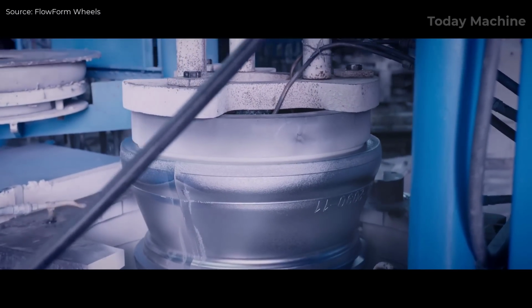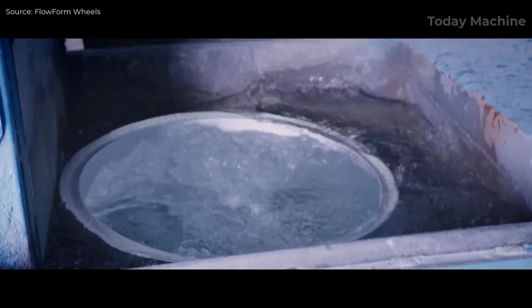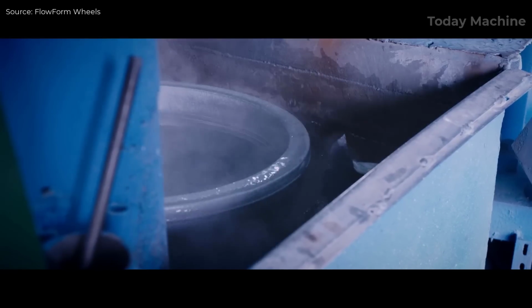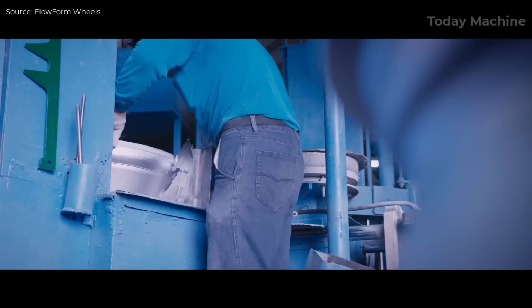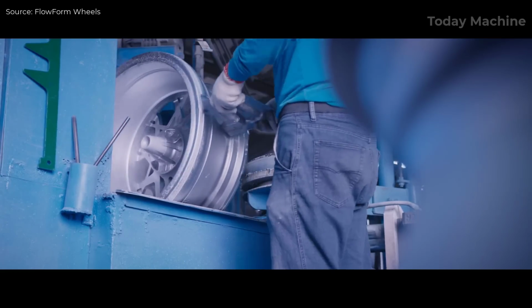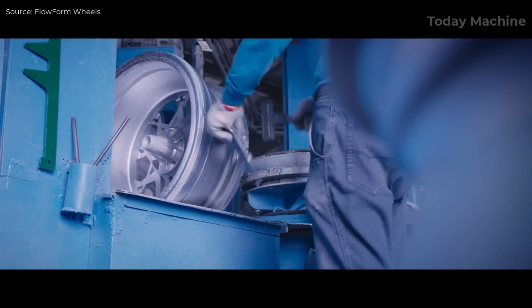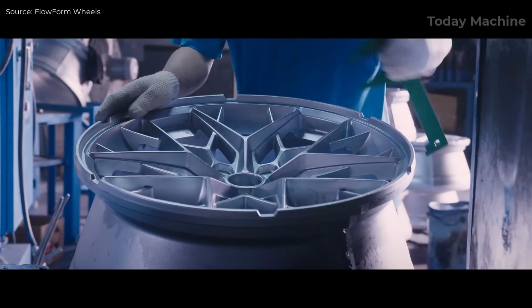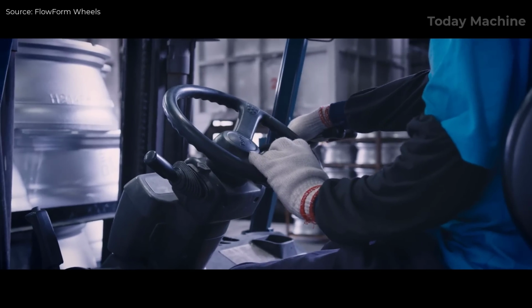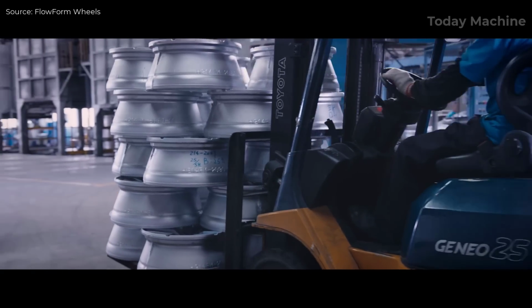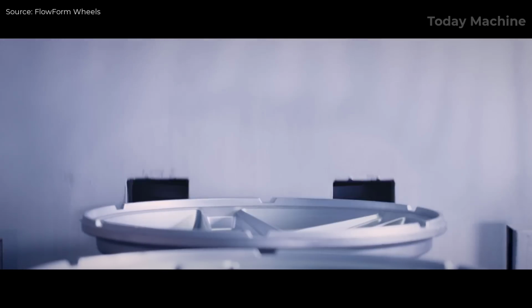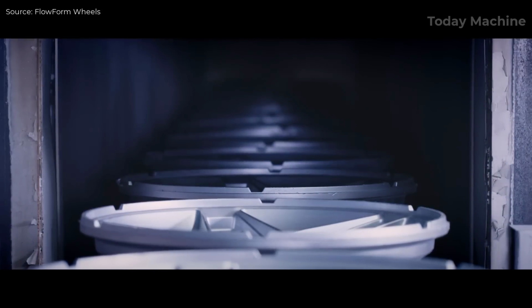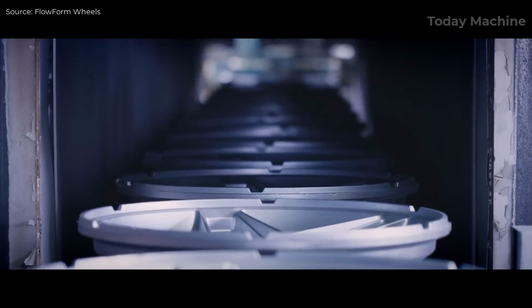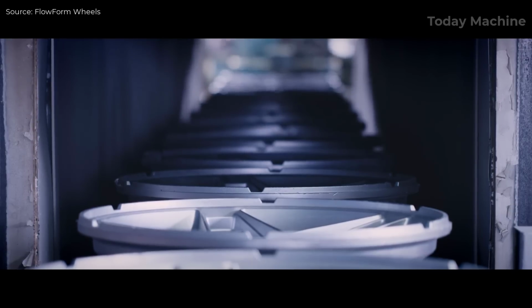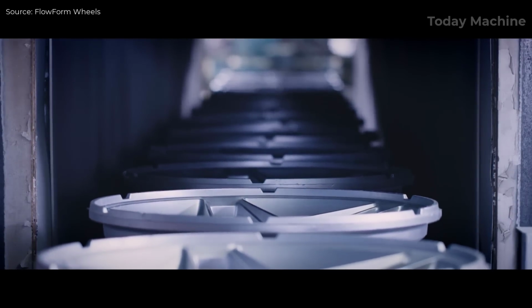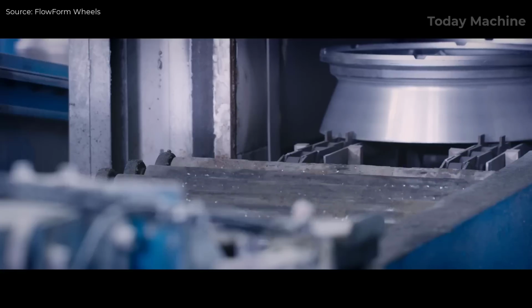Once the aluminum solidifies, the casting is removed from the mold and quenched in water at around 120 degrees Fahrenheit, 49 degrees Celsius. Any excess material, known as flashings, is removed, and the wheel's dimensions are verified to ensure it meets the correct specifications. At this point, some of the wheel's spoke design can be observed, but one key characteristic of flow-form castings is the short rim barrel skirt, which has not yet been fully molded into its final shape. The flow forming process begins with this skirt of material.